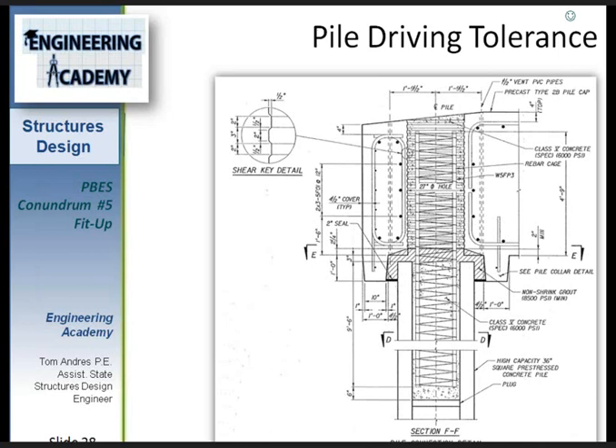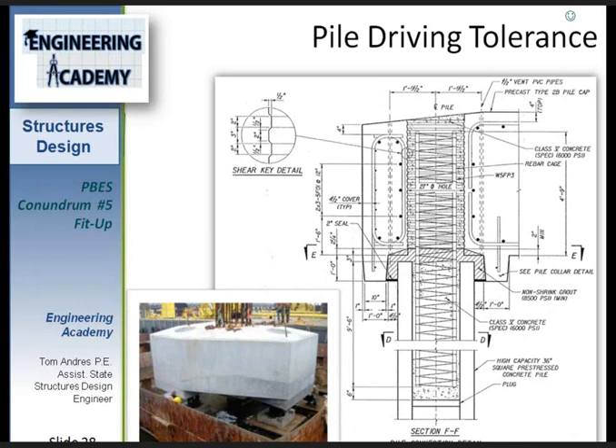Okay. Note that the concrete is performed from the top. There are no hidden pockets from view, so it's pretty easy to inspect. Also, if you look closely, notice the PVC pipes that are vertical there. And this avoids trapping air during the grouting process as you lock in that pile. Also note that there's no steel to corrode at the corrugated interface or the shear key. That's a really, really cool detail there for a water job. Also note that the detail provides a good direct bearing point from the top of the pile to the bottom of the cap. And if you look closely at this picture in the bottom left, you can see the shims that are placed on top of that pile as that precast element gets lowered and adjusted.